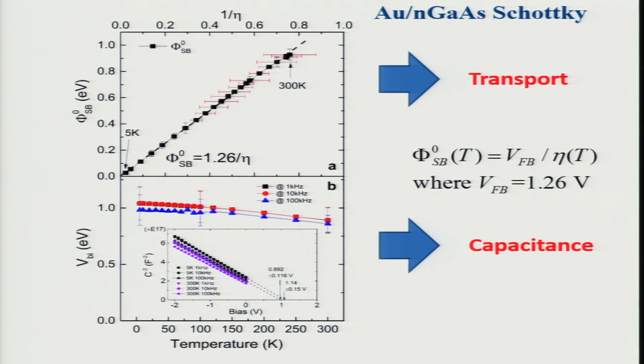This is plotting the 0 voltage Schottky barrier height versus temperature, and it's linear again. I'm essentially repeating the data here, but I want to show you the inverse capacitance. The important part about this is that in forward bias, we're measuring ideality and the 0 voltage Schottky barrier height and getting the flat band voltage without going up to that very high current where RS, the series resistance, would cause a voltage drop, and you just can't get there.